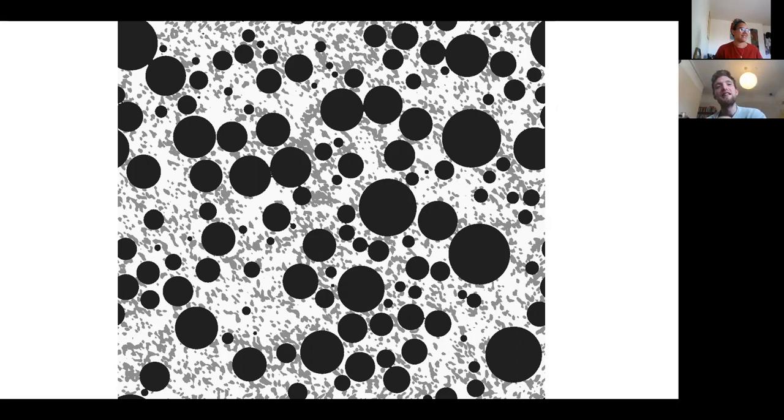I think the limitations at the moment are, one limitation is definitely resolution. In terms of the size of 3D images that we can generate, our networks are limited in terms of memory. So if you have a very high resolution 2D image, we can only go so far in terms of what we can capture. Often you have to downscale in order to make this work, but that is something that we will try and get around in the future.